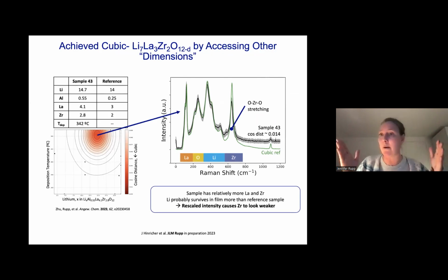And we also go down to a more granular level, and I want to show you that. For instance, here we have an example for the cubic crystalline films, right? So that's the cubic part. Before it was pyrochlore. Over there was more the tetragonal phases. And we can show you, for instance, from several samples and their references, how the different bonds are actually affected, because you are not static in the phase. Even without a first order phase transformation, you see already small changes in the bond vibrations because of reordering, and we try to understand how significant they actually are later on for conduction, phase stability, and electrochemical stability at the battery cell level.